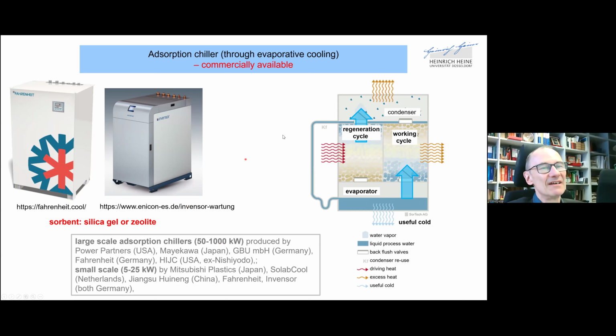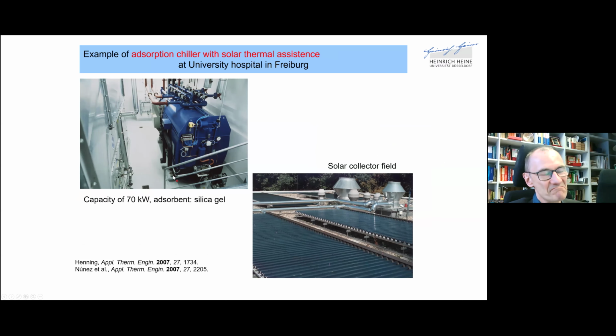And all these devices run in this two-chamber system or two-cycle mode. One chamber is in the working cycle, and the other chamber is in the regeneration cycle. And you can switch between these two cycles in a few minute interval. So it's a very quick working and regeneration cycle. And I come to it later why it can be so quick. So here is actually a device in real life with a capacity of 70 kilowatts using the adsorbent silica gel. And this device shown here is combined with a solar collector field on the roof of the building, where the driving heat is now generated by solar thermal energy.